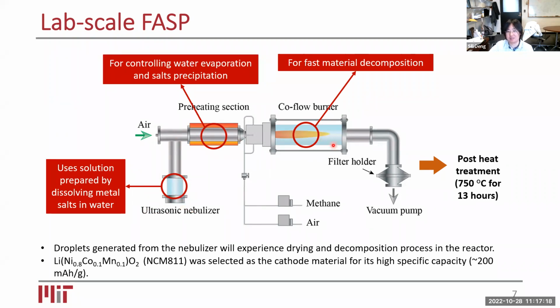That's why it's called flame-assisted spray pyrolysis: we have a preheating section that does not contain flame, which gives us a more controllable, especially gradient-controllable, heating of this precursor. And then we have a co-flow burner where we have this flame to produce both the high temperature as well as the oxidative environment for the decomposition of the precursors. And after these two processes, we can get solid particles, which are gathered by the filter. And then we take the materials and follow the industrial procedure to do the post-treatment for a long time.